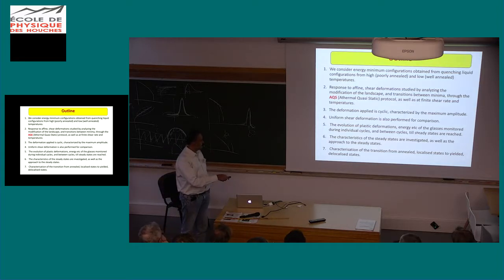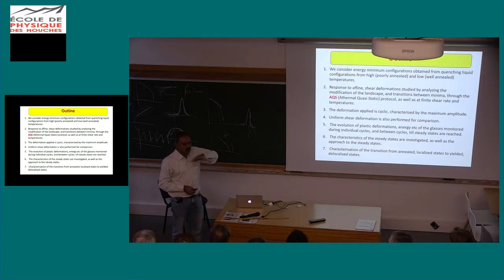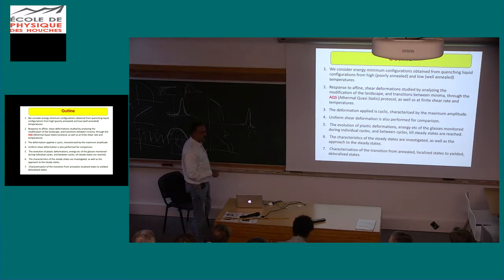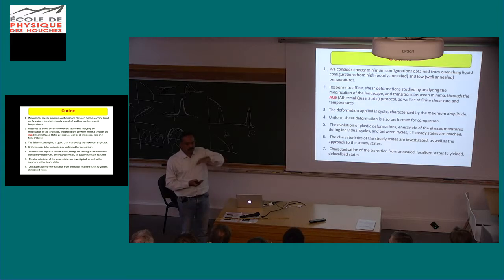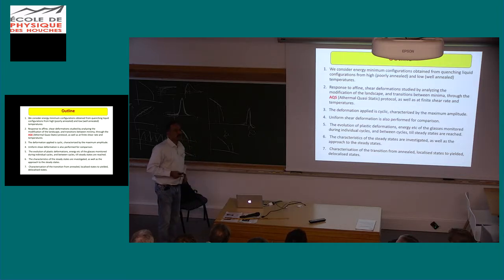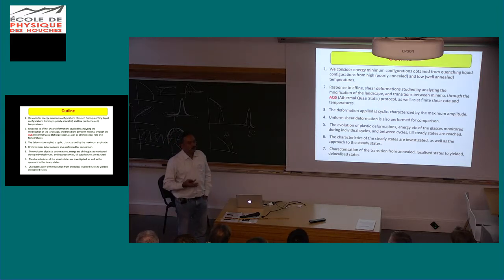And what one normally sees is that some kind of a steady state is reached after the application of cyclic deformation through a large number of cycles. The characteristics of the steady state are investigated, as well as the approach to the steady state. One caveat here is that the steady state when one is deforming a glass uniformly usually means that you've gone beyond the yielding point and you're in a flow regime. And in the case of cyclic deformation, one doesn't always do so. It depends on the amplitude of deformation, whether you go beyond the yielding point or not. So steady state for us means that after the application of a number of cycles of strain, one has reached a state where the properties of the glasses are not changing, or at least not changing very much.